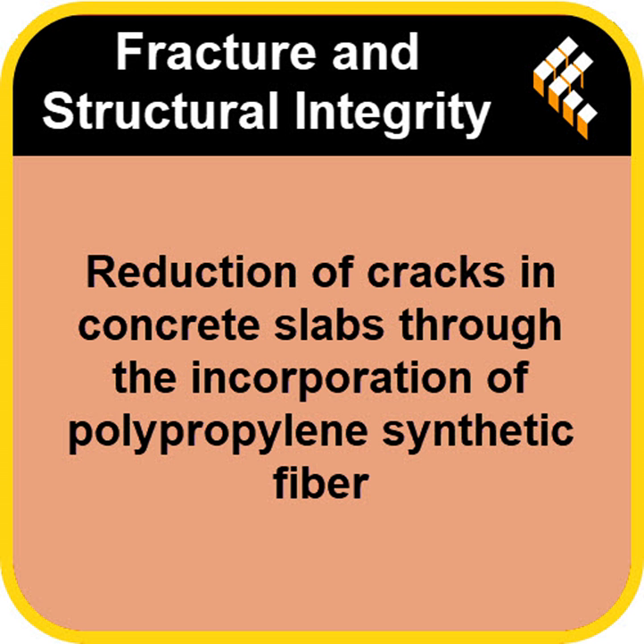So the mechanism here is that the fibers are physically blocking the water's escape routes. Exactly. They interrupt these tiny capillary channels. They're like millions of tiny dams, holding moisture in so the cement can hydrate properly. It's a powerful first line of defense. That confirms the immediate benefit, but the real question is about long-term durability, right? What happens at 28 days when the concrete is supposed to be at full strength?